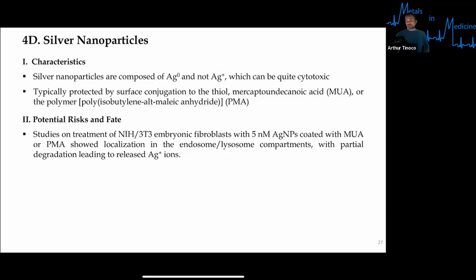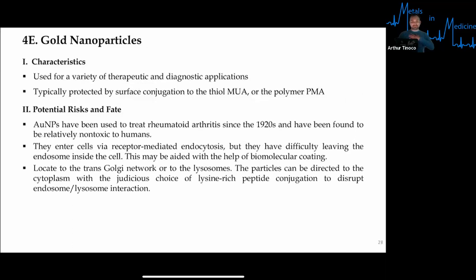So studies on the treatment of NIH3T3 embryonic fibroblasts with 5 nanomolar silver nanoparticles coated with MUA or PMA show localization in the endosome, lysosome compartments, with partial degradation leading to released silver ions. So that actually has the potential to be hazardous, the release of the silver ions.